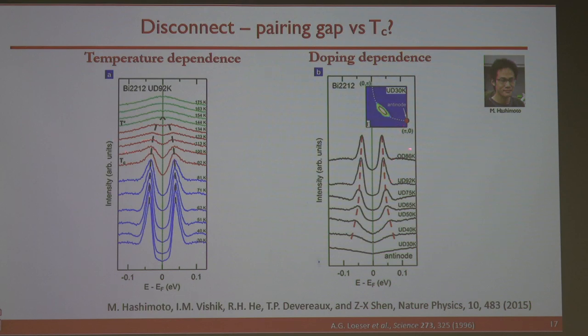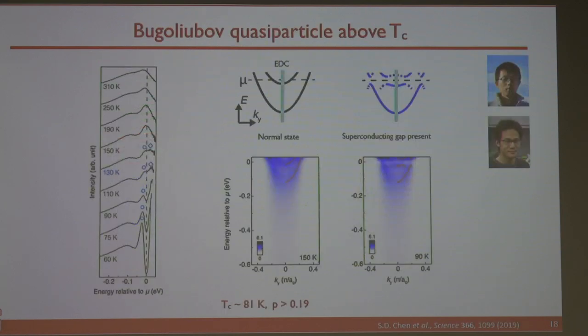Now, another thing: if you look at the d-wave antinode, that's where the gap is maximum. If the Cooper pair strength is a measure of TC, then the size of the gap and TC should be correlated. Again, as you go to the underdoped regime, the gap gets bigger, even though the TC gets lower. Again, it's saying that there's no connection between TC and the pairing gap in this vast regime of doping. Okay. A question.